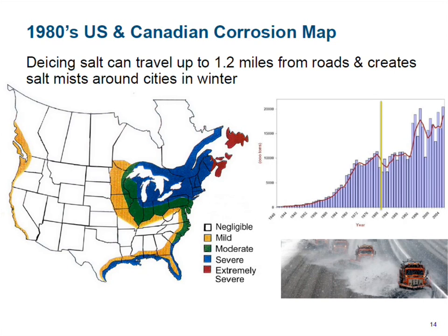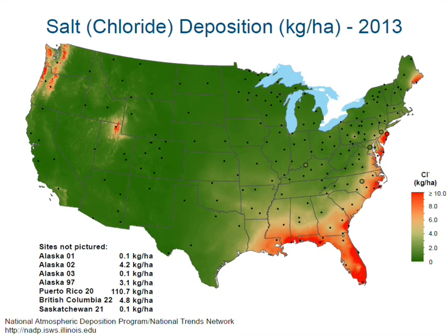This is a 1980s US and Canadian corrosion map done by the automobile companies. Ignore the West Coast because that's not particularly accurate, but you can see in the 1980s the effect of de-icing salt and industrial pollution around the whole Great Lakes, well, what was really the heavy industry belt. I also show on the right data from the Salt Association and the fact that we have essentially doubled de-icing salt use since the 1980s. And that has changed the map.